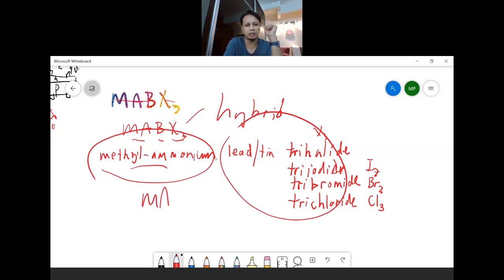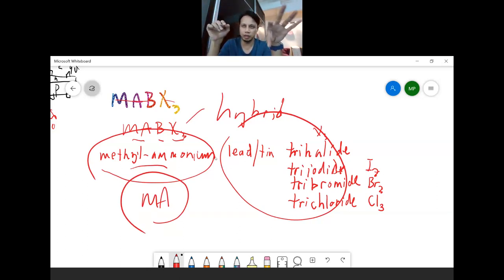The methyl ammonium part is not stable, it easily decomposes. When it decomposes, it no longer remains methyl ammonium lead triiodide, it becomes something else, and that something else causes the change of the structure and therefore the degradation of the efficiency. There are many more reasons, such as metal migration, and a few more reasons that are not yet understood by scientists at the moment. But one of the possible root causes is the decomposition of the methyl ammonium. So scientists now try to replace the methyl ammonium with some other molecules in order to retain the efficiency of the solar cell.